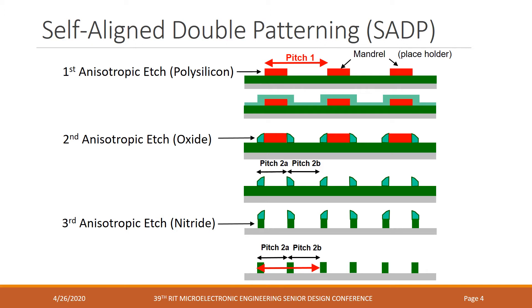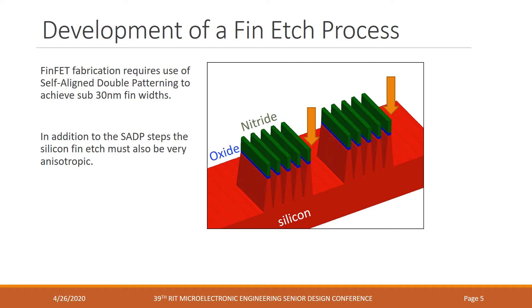Another step forward is the ability to use multiple patterning techniques — a technique that can create devices at a pitch smaller than what you can directly print on the wafer using lithography. When using self-aligned double patterning, the etching all needs to be highly anisotropic. A single self-aligned double patterning layer has a minimum of three required anisotropic etch steps. These steps could then be used to realize structures such as sub-30 nanometer fin FETs here at RIT, allowing students to get hands-on experience with modern FET structures.